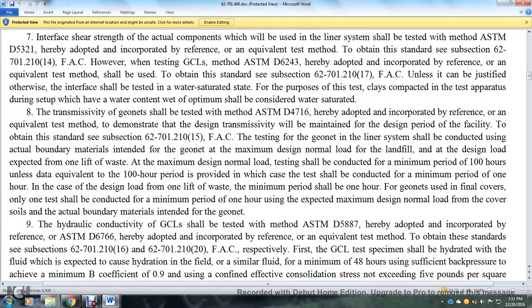8. The transmissivity of the geonet shall be tested with the method of ASTM D4716, hereby adopted and incorporated by reference, or an equivalent testing method, demonstrating that the design transmissivity will be maintained for the design period of the facility, to obtain the standard, section 62701 210 15. F.A.C. The testing of the geonet in the liner system shall be conducted using the actual boundary materials intended with the geonet at the maximum design normal load for the landfill, as the design load expected with one lift of waste at the maximum design normal load.